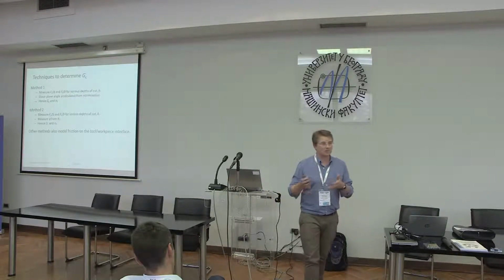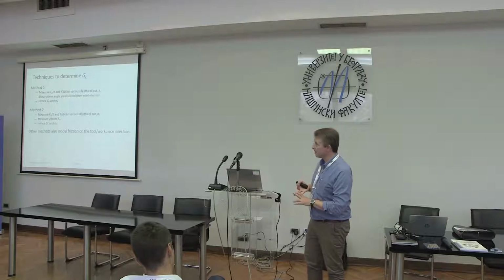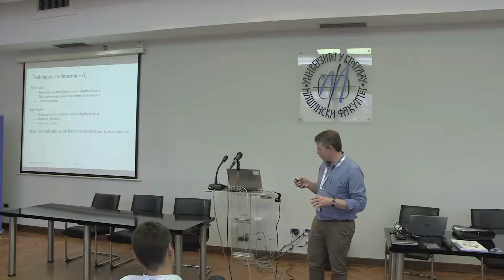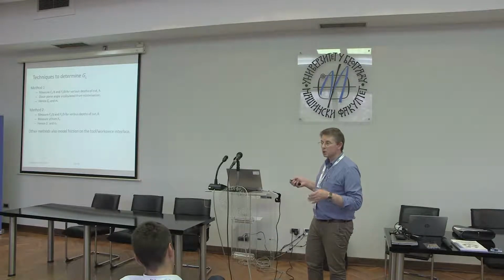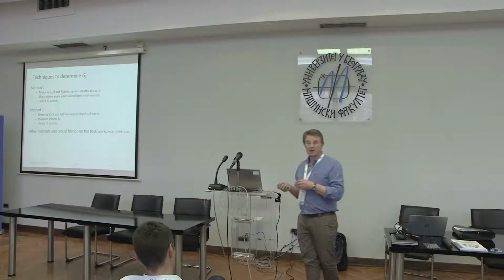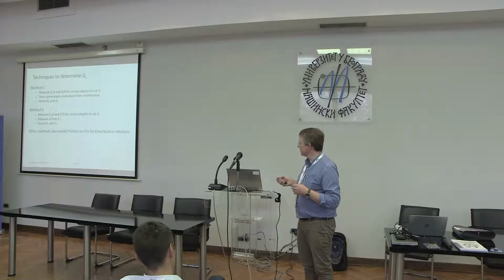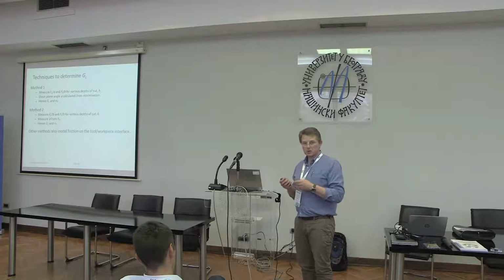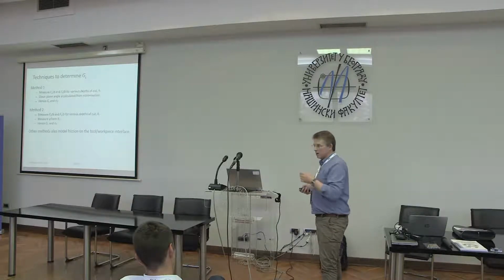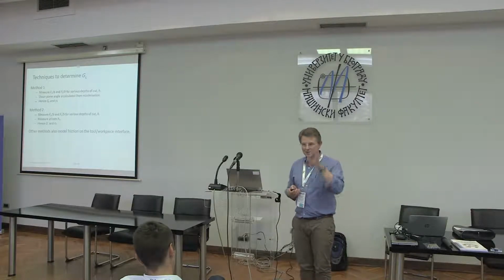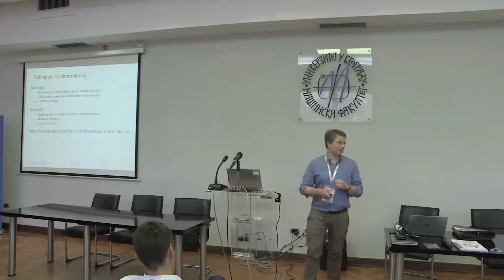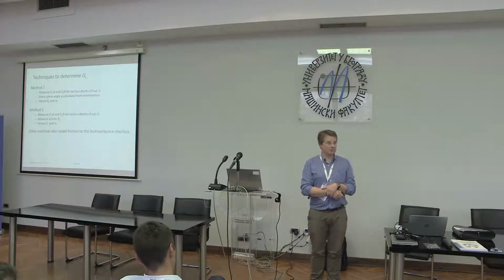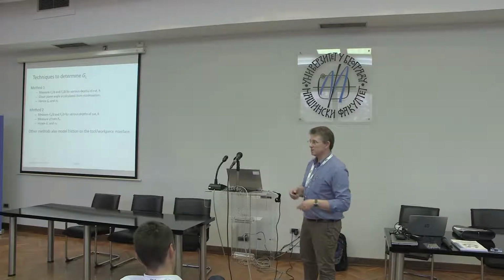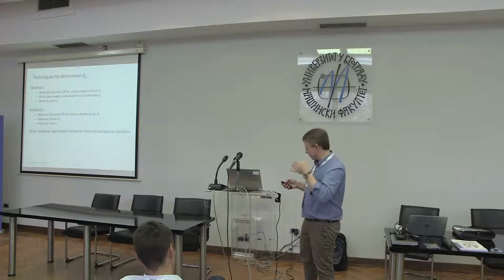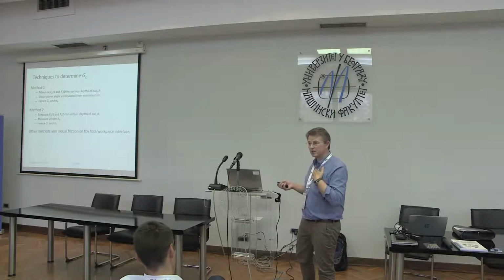Now, there are lots of different ways that you can analyse this problem. We talked about equilibrium, we talked about energy methods, but all of them tend to require that you measure the cutting force, normalised by the width of the specimen, and the transverse force, normalised by the width of the specimen, as a function of the cut thickness. And there are two ways that you can then proceed. You can either go and find the chip and measure the cut thickness, HC, okay, which is good if you've got a careful student. Sometimes it's difficult to find the chips after they usually spiral off, and sometimes they ping and you have to go and find them. So there's a problem with chip identification sometimes, but if you can go and find the chip, you can measure it.